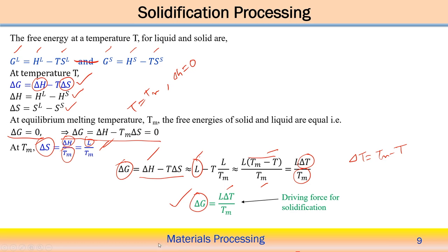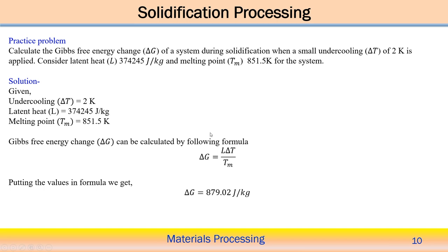But solidification occurs exactly close to the melting point temperature, where delta G, the change of the Gibbs free energy, is equal to zero. One practice problem: calculate the Gibbs free energy change of a system during solidification at a small undercooling, delta T equal to 2 Kelvin only. Consider the latent heat and the melting point temperature of the system as given. So the degree of undercooling, latent heat and melting point are given. From here delta G, the driving force, can be calculated as L delta T by Tm.